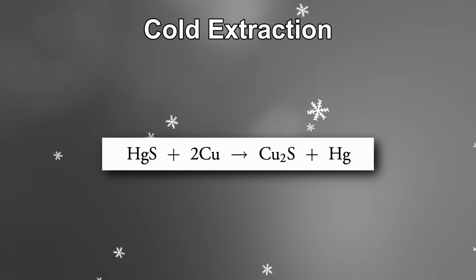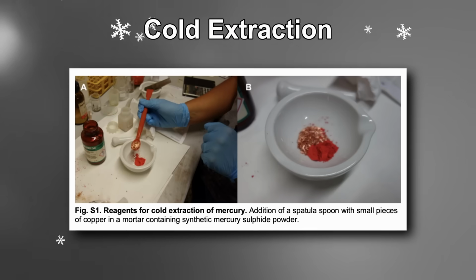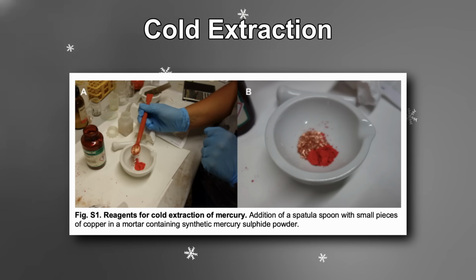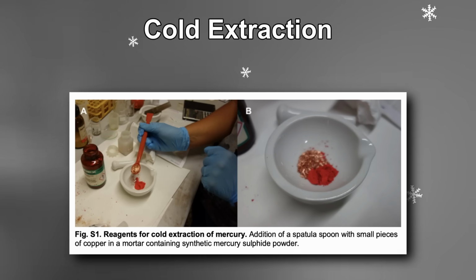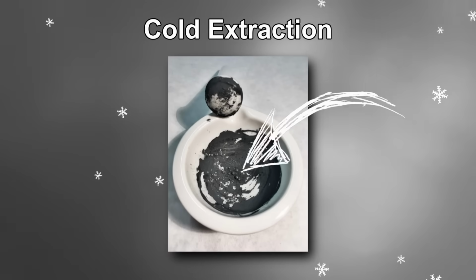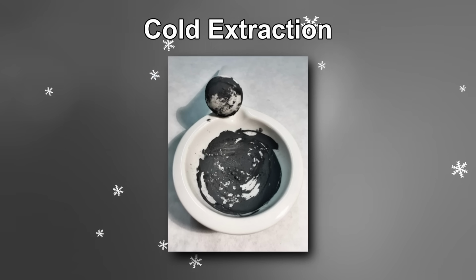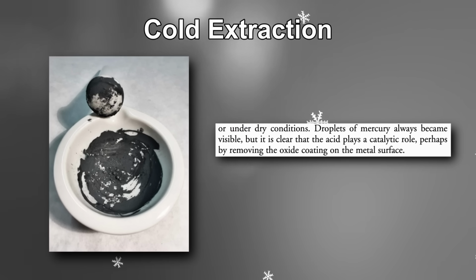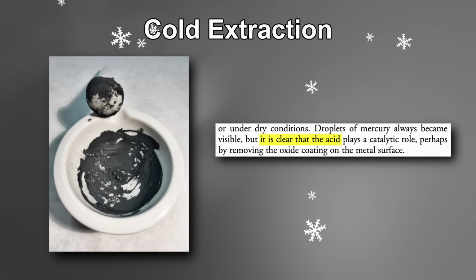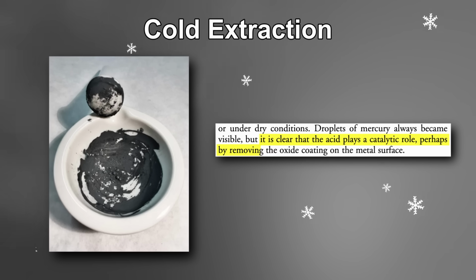The researchers recreated this procedure by grinding synthetic cinnabar with copper turnings and acetic acid. After an hour, they started to see droplets of liquid mercury forming. The researchers also said that it is clear that the acid, meaning the vinegar, plays a catalytic role, perhaps by removing the oxide coating on the metal surface.